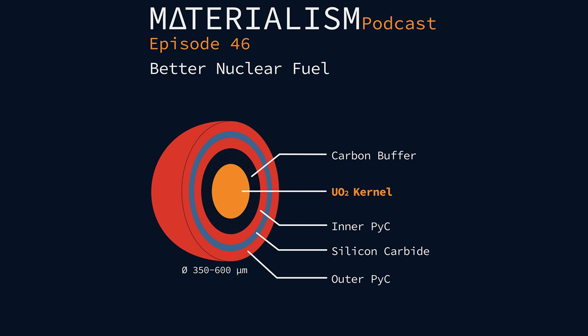Oh, okay. Gotcha. So you can include other material that you don't necessarily have to process to the same extent and still end up getting the same results. And so you're taking advantage of that fission process to get what you need eventually. Yeah. So that's where they were using thorium, because it would eventually, just through the process, become fissionable. And for the most part, these were all carbides. And the reason for that is because carbides can go to much higher temperatures. And so they were theoretically able to get much better results. But these were susceptible to hydrolysis reactions during fabrication. And so they would corrode or oxidize. And it was a problem.